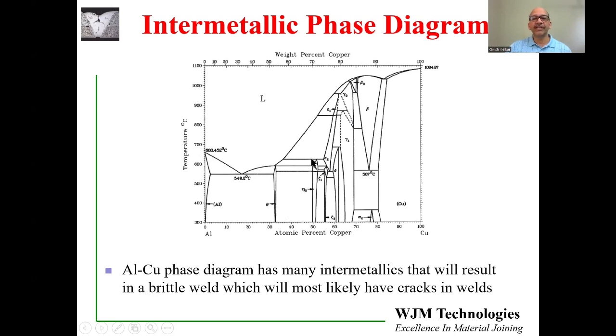When you see a lot of these vertical lines over here, that tells me that there are a lot of reactions between aluminum and copper and they form different reaction products. Almost always these reaction products are brittle. So just looking at this phase diagram, I would predict that if you weld aluminum to copper with a lot of mixing of the two, under normal circumstances you are very likely to have cracks in the welds.